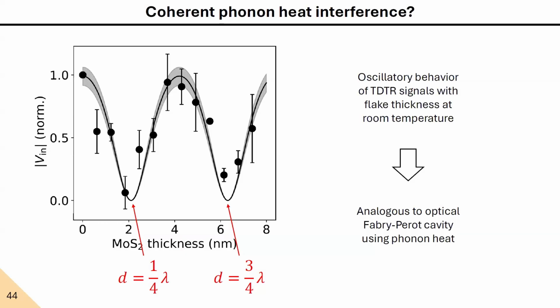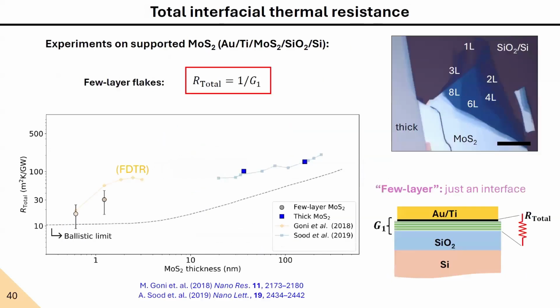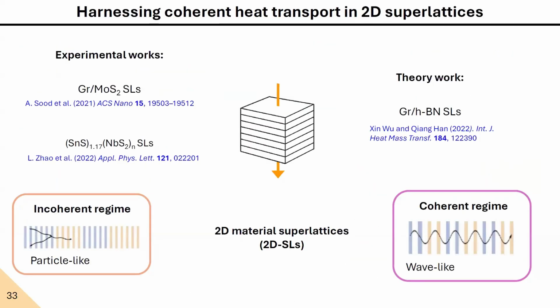So you said there was a theoretical work talking about coherent transport, and for 2D materials there are some works on this. I don't know, yes, but it was with heterostructures, no? But for molybdenum disulfide, there are no other reports on that, no? Molybdenum disulfide is considered there. They perform stacks of graphene and molybdenum disulfide, but it's not a superlattice in the sense that it is not periodic. Of course, it's periodic, but the thickest sample they studied is 5 layers thick: graphene, molybdenum disulfide, graphene, molybdenum disulfide, graphene. So eventually a superlattice would be something periodic and repetitive over a longer scale.